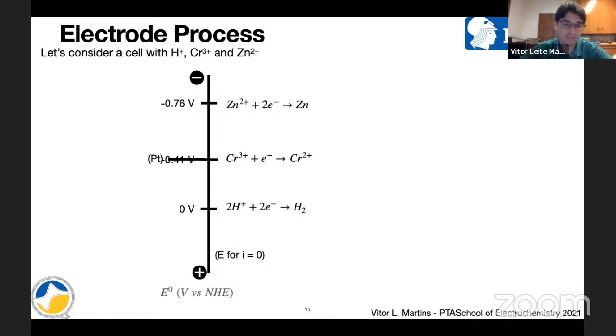If you keep increasing and go through this value here, then both reactions will occur, right? So you have enough energy of the electrons for hydrogen to be reduced, and also enough energy now for chromium to be reduced. So both reactions are occurring at the same time. So the current that we are measuring at a potential like that will be due to two electrochemical reactions occurring at the same electrode. So this case is for platinum.